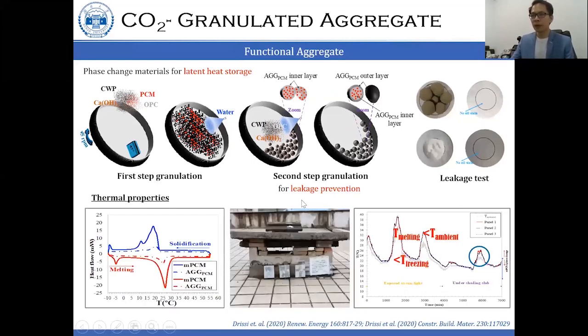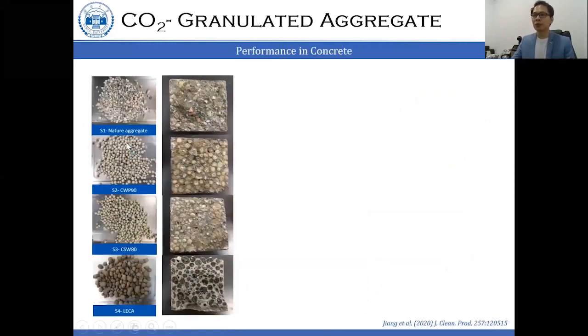So we have done the leakage test, and the result is promising. Also, we have carried out the thermal properties test and incorporated the PCM aggregate in the concrete panel and exposed it to the indoor and outdoor conditions. And we found that we recorded 1 degree C lower for the PCM aggregate panel. So reflecting that they have a better thermal performance and also potential for energy saving. And we're also interested to see how the aggregate will perform when we incorporate it in the concrete.